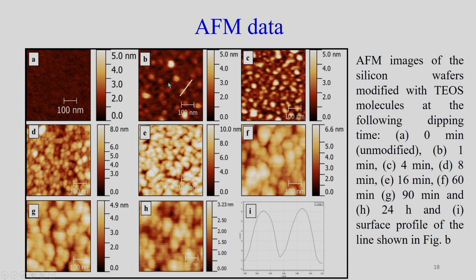So, what it says is with increase in time you can see there is a formation of small islands, it looks like small patches, and then there is a filling up, and after the filling up we can see the grain size or the particle size also increased here. So, it looks like first there is a filling up, then there is a reorientation.